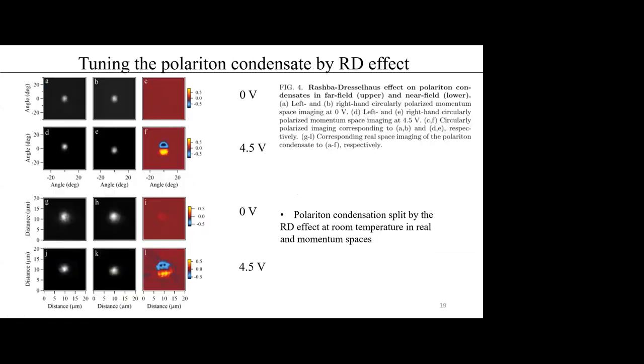Okay, finally, we measure the spin polarized momentum space and real space images above threshold when the voltage is 0 volts and 4.5 volts. It is clear that the polariton condensate with opposite spins is split both in the far field and near field at the voltage of around 4.5 volts. The two spin components of the polariton condensate gain non-zero momentum, and the polariton condensate is split by around 0.8 micrometer. So these results clearly show the Rashba-Dresselhaus effect on the polariton condensate at room temperature.